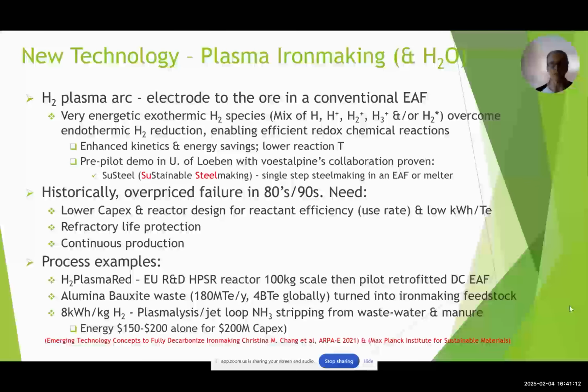Historically, it's been overpriced and failed in the 80s and 90s. We need lower capex and reactor design for the reactant efficiency. Its refractory life needs protection, and we need to have continuous production. Some of the examples are hydrogen plasma reduction. There's a 100 kilogram scale pilot, which will then be retrofitted to a DC arc furnace.